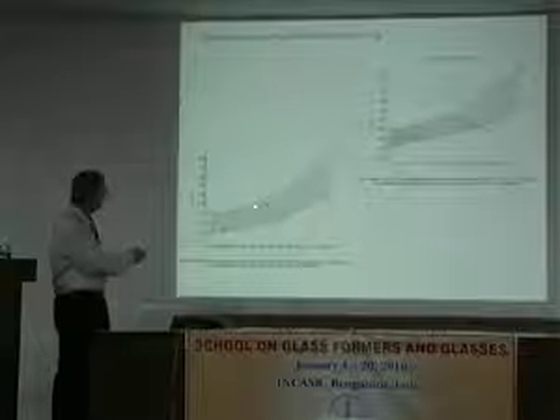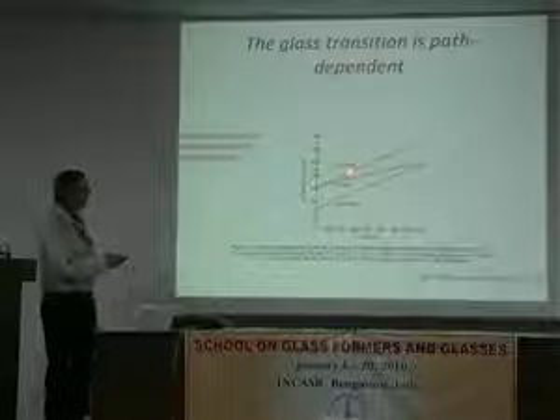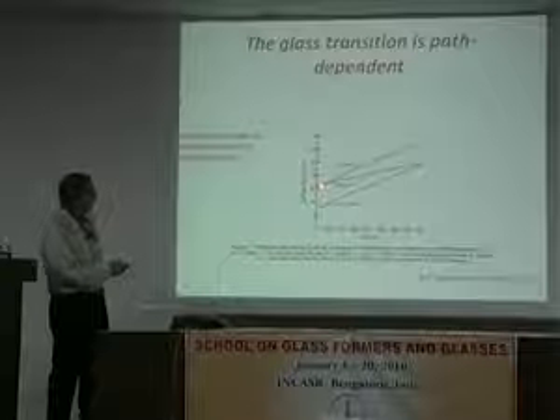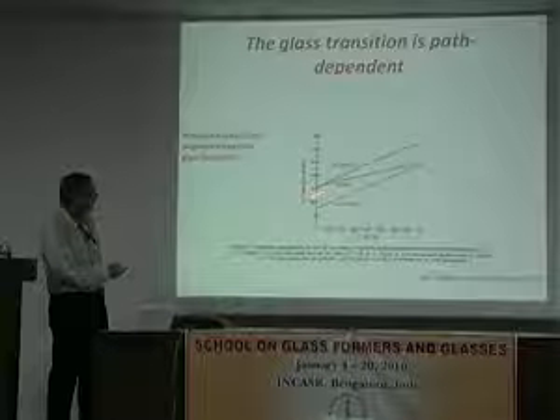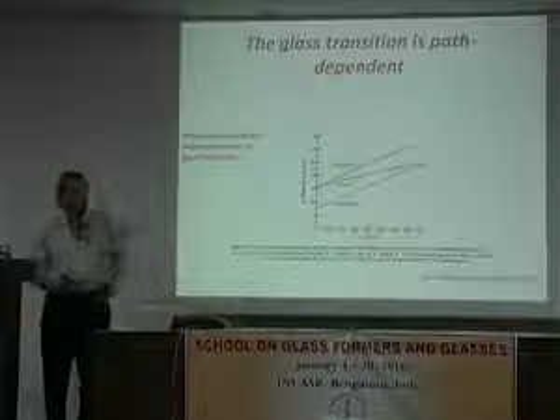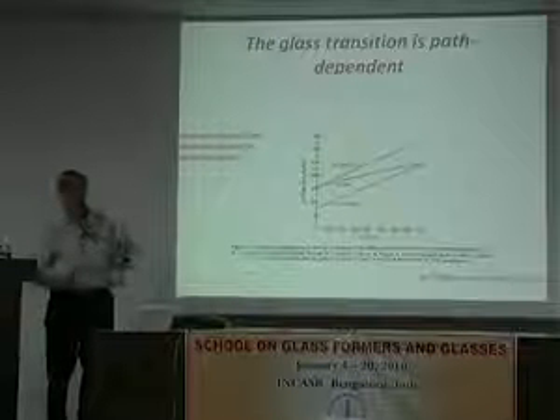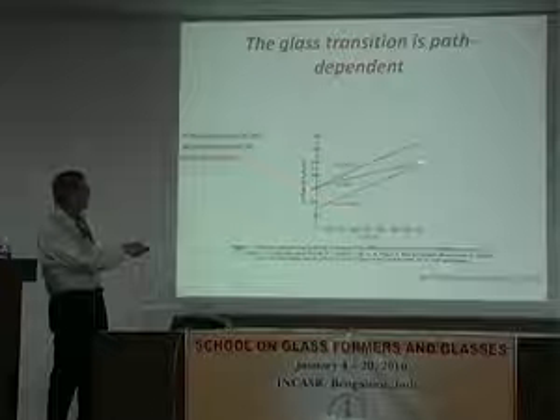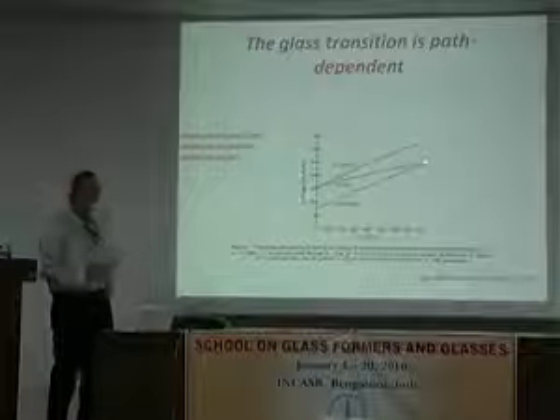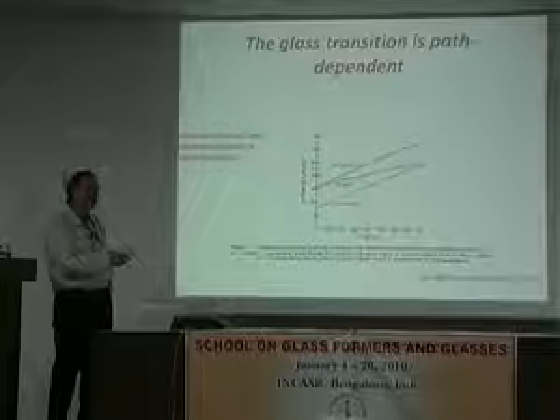And the comparison is made with this one where McKenna and Goldstein said, well, let's form the glass, and then we're going to pressurize it in the glassy state. And we're going to see, is this surface the same as this surface? And is the glass line, the one that we're going to be interested in, the glass line as a function of pressure, the same in the two cases? Okay. Well, the next figure shows that indeed it's not. In fact, we see that there's a factor of about 2 difference in the slopes depending on exactly what path I took to create my glass, how I create my glass surface. Okay, so that's already important because that tells me if, for example, I need the derivative of the transition with pressure, well, you better know how you measured it because this factor 2 is quite large.